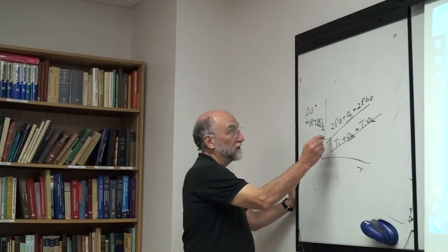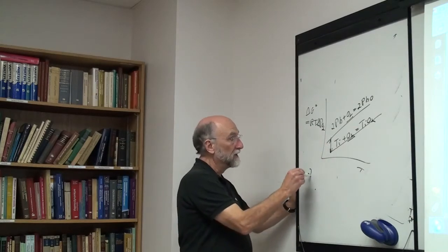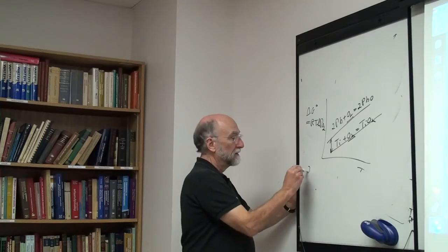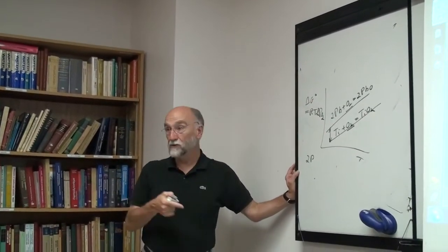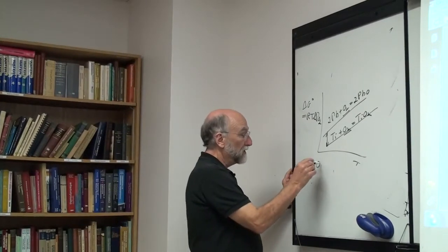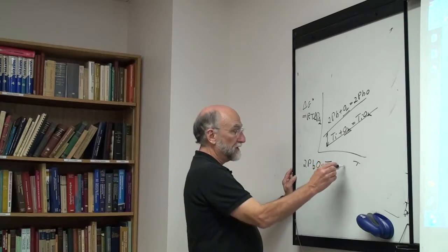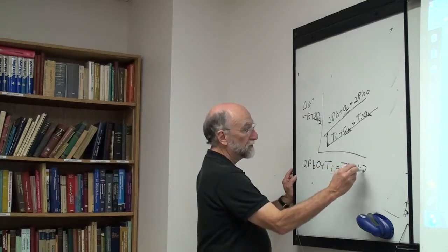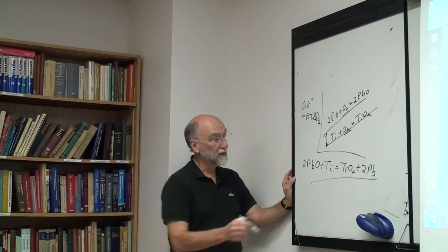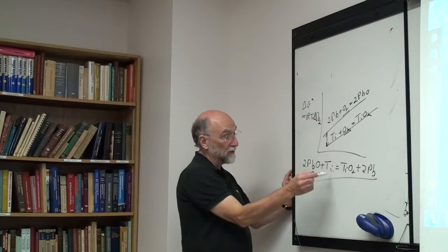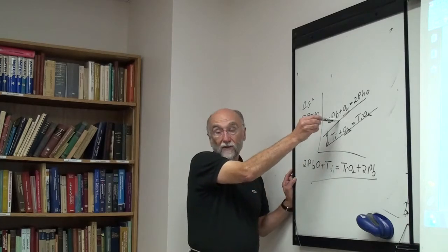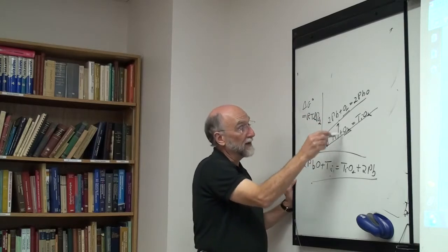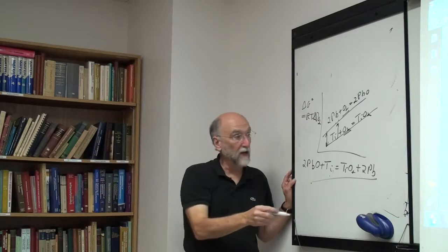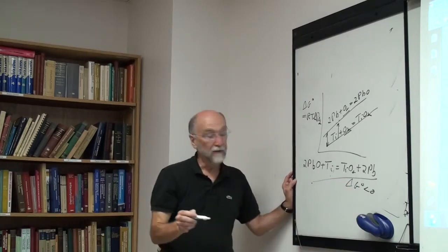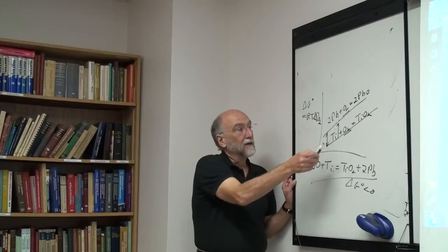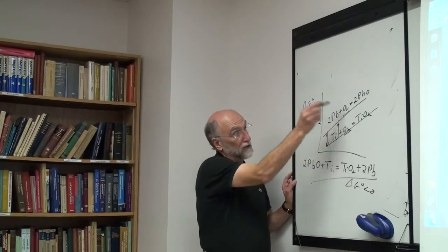This would simply mean if you wanted to do the reaction between them: will titanium reduce lead oxide, or will lead reduce titanium oxide? Okay, you write 2 PbO plus titanium equals TiO2 plus 2 lead. That's the balanced reaction. The oxygens cancel out. This reaction is this minus this. So now I just look at the Ellingham diagram and I see that the titanium line is below the lead line, so the delta G for this reaction is negative, because this line is below this line. It's just when I subtract the two Gibbs energies, the oxygen cancels out.